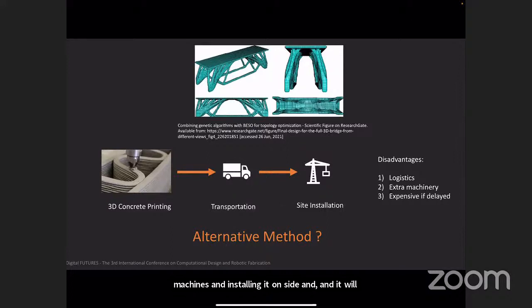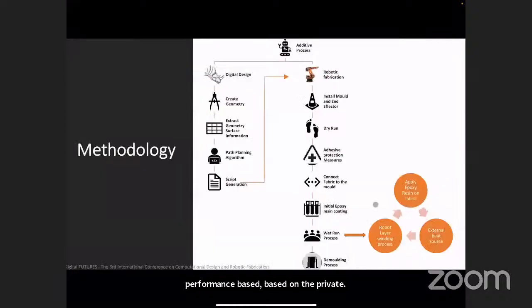So the alternative method we thought of was to do a composite structure, which is more material efficient and also structurally performance based, on the hybrid double hybrid structure developed here. The methodology is to use fiber reinforced polymer fabric to fabricate a formwork, transport the formwork to the site, install it there, and then cast concrete for both standard and non-standard cross sections.